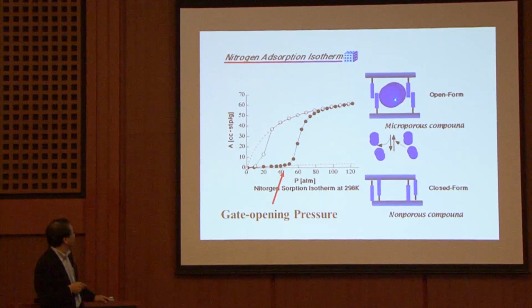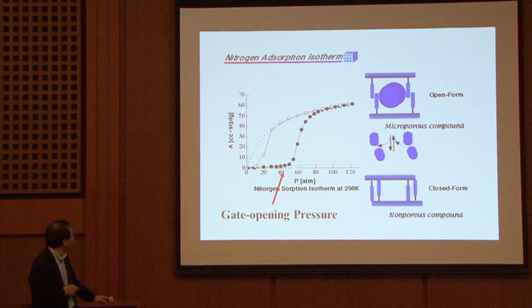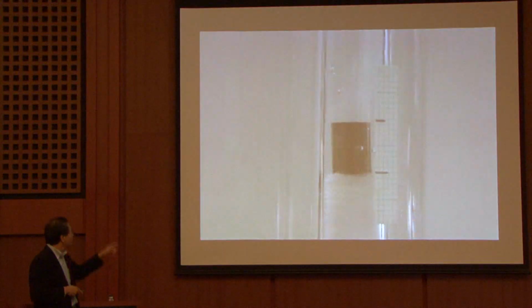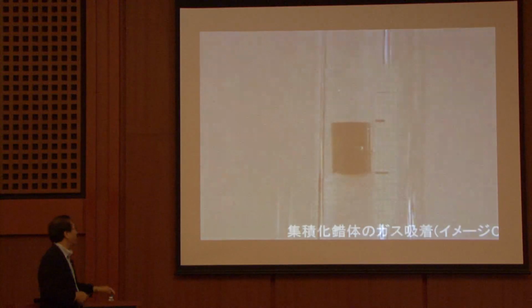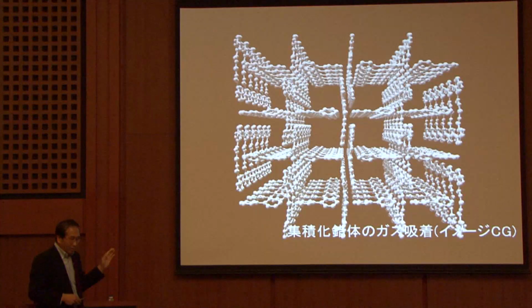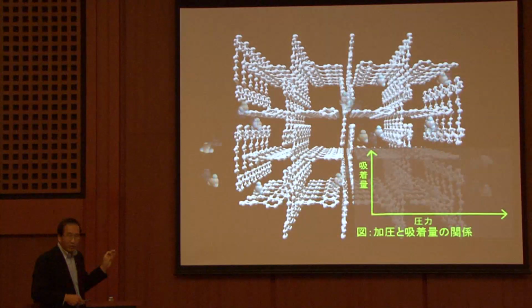So, removing gas molecules, and then applying the gas pressure at room temperature. This is nitrogen, and at this point, the abrupt adsorption occurs in this way, and desorption here. We observe the hysteretic sorption in this case. So we call this the gate opening pressure here. This is a powder microcrystalline sample. We apply the pressure. The structure expands to accommodate gas molecules. What happens in this case? Still, we want to know what happens.